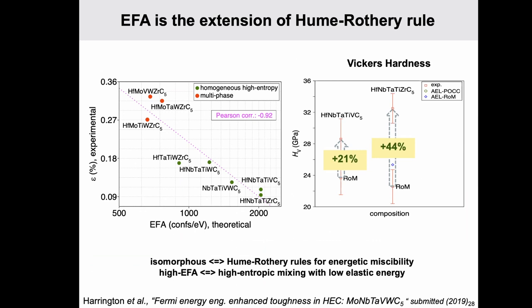As such, if I require more energy, then I need to do more work to do the same dislocation, which means that if I put in constant work, because I'm pushing the force at the same amount in as an indenter, I will have less movement. So that's the reason why high entropy systems tend to have a higher hardness. Some will be much harder, some will be slightly harder, but you always expect a higher hardness.